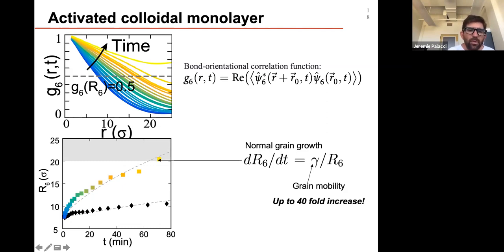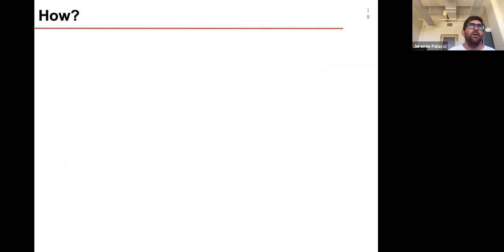And so from the dashed line, we could extract the grain mobility. And what we see is that the grain mobility is 40 times larger in the case of activated monolayers than in the case of thermal monolayers. And so the question was, what's happening? What is driving this increase of grain mobility?